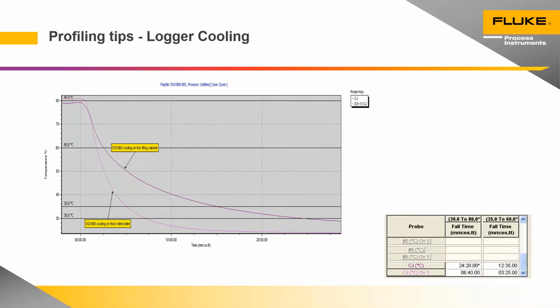When we placed the logger on a thin metal filing cabinet to cool back down from 60 to 35 degrees, it took in the region of 12 minutes. When we did exactly the same thing, but placed the data logger on a thick steel plate, a nice cool surface, it cooled down in 3 minutes, or 3.5 minutes.